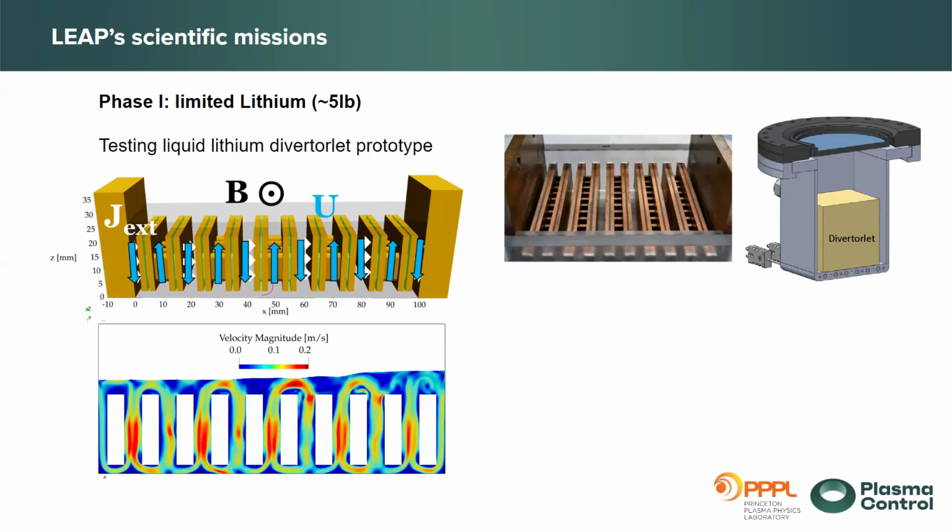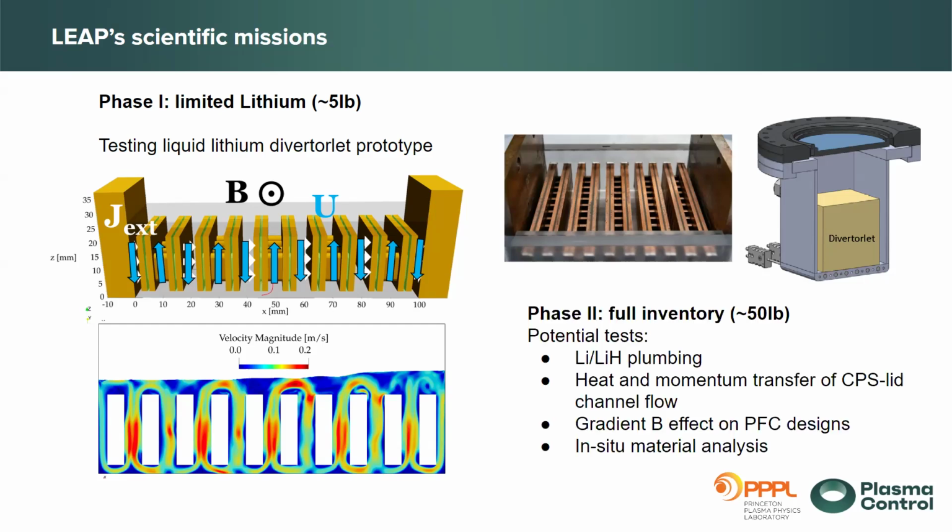The interesting thing about liquid lithium is that right now we do have a prototype with Galinstan, and Galinstan has different material properties from lithium, including different surface tension and different density. All of these can be further verified with a liquid lithium prototype, and we can actually build it to a size that is relevant to what the reactors, or NSTX, or maybe the CORE-EDGE facility would want.